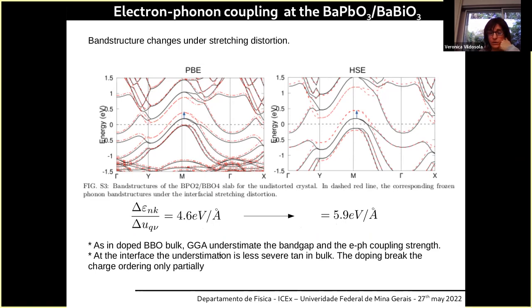As in doped BBO, GGA underestimates the band gap and the electron-phonon coupling strength. At the interface, the underestimation is less severe than in bulk. The doping breaks the charge ordering only partially, because you see that the bands that come from the lead don't shift, don't couple to the phonons. The only electrons that couple to the phonon modes are the ones that are linked to the bismuths, right? Because lead is not close to a valence skipper situation, so it doesn't contribute to the electron-phonon coupling. So here the breaking of charge ordering is partial because bismuth 5+ is still empty, right?